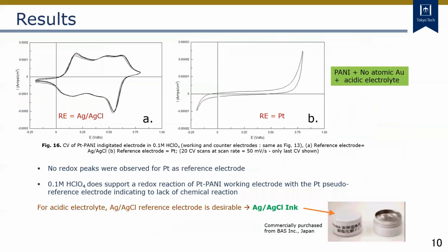However, the electrochemical response in acidic medium is different than in alkaline medium. Cyclic voltammetry was measured with a commercial Ag/AgCl reference electrode and the platinum of the planar electrode respectively. Results show that depending on the type of the reference electrode, the redox process is different. For planar electrodes, the commercial reference electrodes are bulky. Therefore, on a planar substrate, we investigate Ag/AgCl ink in order to reduce the form factor of the sensor.